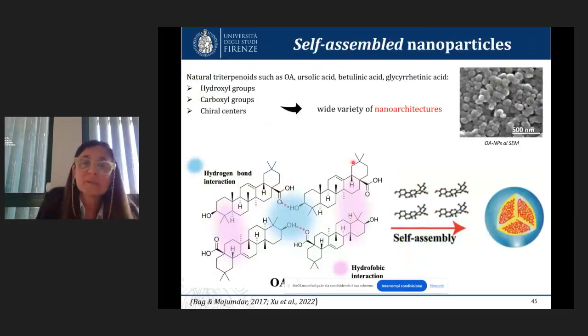In the literature, there are many studies that reported that natural triterpenoids, such as oleanolic acid, ursolic acid, or glycyrrhetinic acid, can self-assemble in nanoarchitecture, in nanoparticles, due to the presence inside the molecules of hydroxyl, carboxyl, or chiral centers. Here, in this figure, there is the ability of oleanolic acid to interact and to produce nanoparticles after self-assembling.